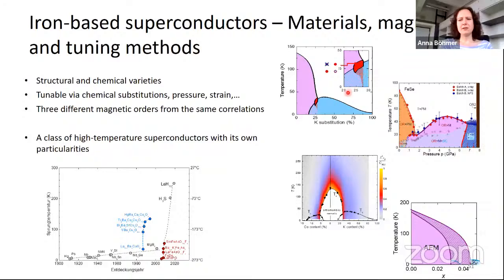Maybe one thing you can learn, it's a little small here, is from this line in the phase diagram. It means that the superconductor would still rather prefer the stripe magnetic order than the tetragonal spin charge density wave order. So it prefers the pink to the red. You can see that because the red region shrinks inside the superconducting state. So there are different degrees of competition between all these phases.